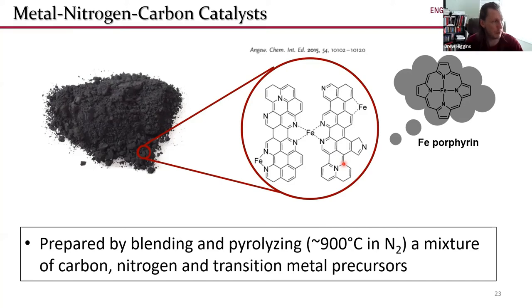And the beautiful thing about these metal nitrogen carbon catalysts is that they're prepared by fairly straightforward procedures. You can essentially take any source of a transition metal, any source of carbon, any source of nitrogen, blend them together and heat them up to about 900 degrees Celsius. And you're going to form these types of active sites in that catalyst material and ideally have some activity that comes with that. There's obviously a large degree of optimization and improvement that goes into these syntheses, but at the very basic level, they're relatively simple. And simple is nice because simple means cheap and simple means scalable.